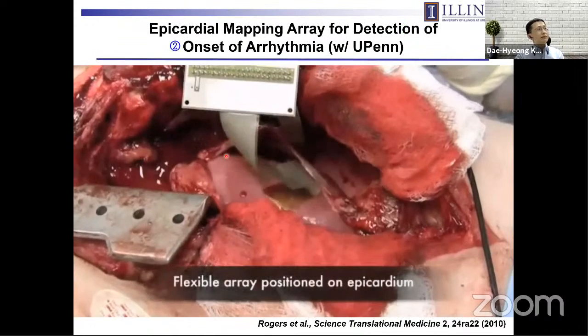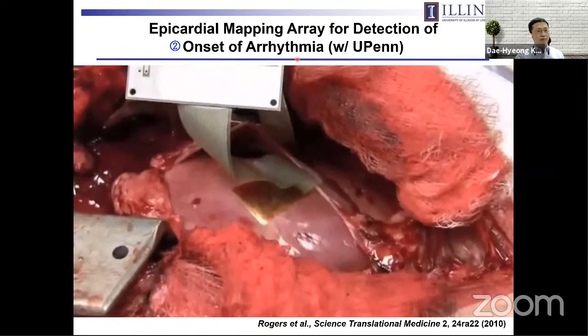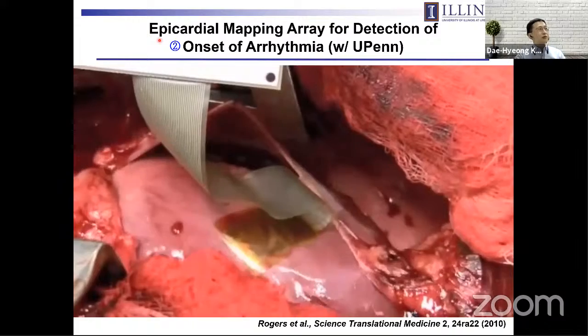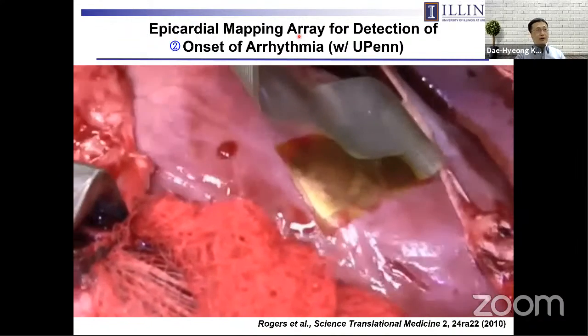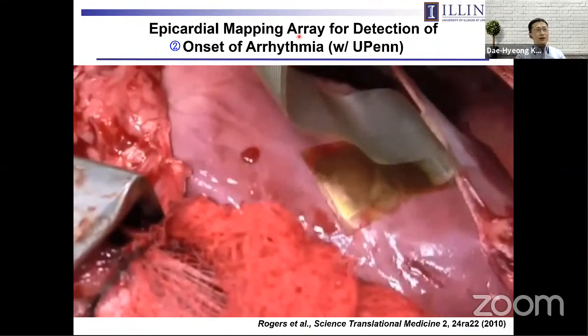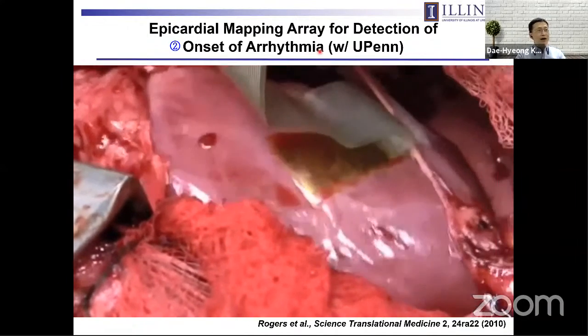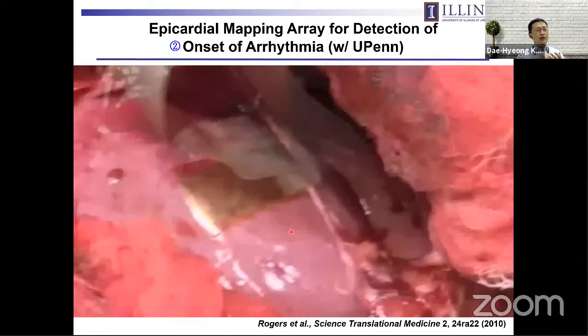In another example, again back in 2010, we worked on the epicardial mapping array for the detection of the onset of arrhythmia in collaboration with the researchers at UPenn. In this case, we used ultra-thin doped silicon nanomembrane to fabricate a multiplexed electrode array. Since we used very thin, 300 nanometer thick silicon nanomembrane, the flexural rigidity of the silicon could be reduced dramatically. So the entire multiplexed array could be very much flexible.